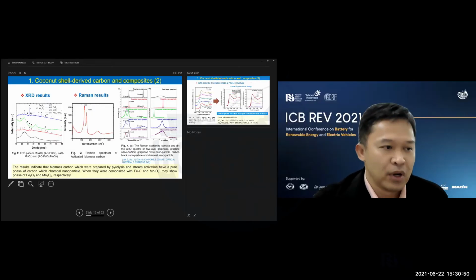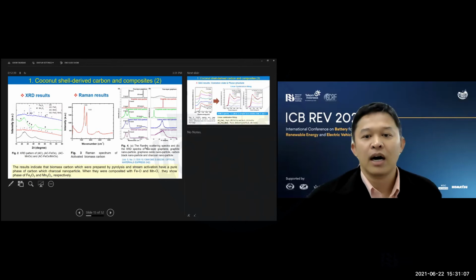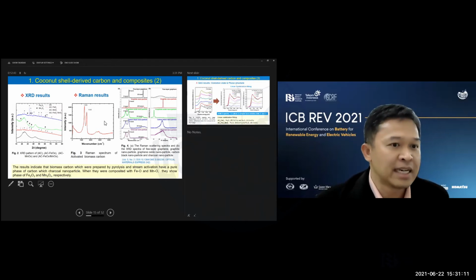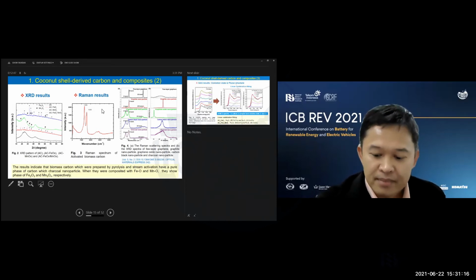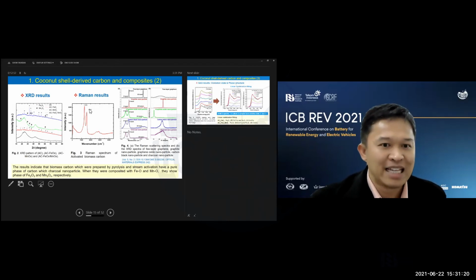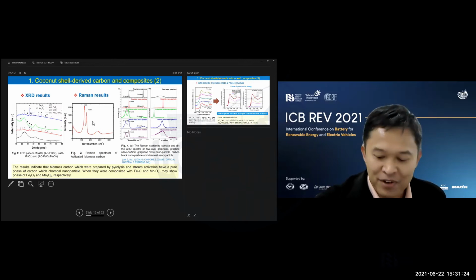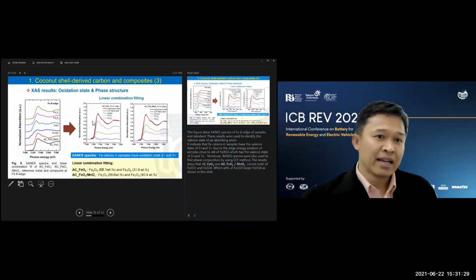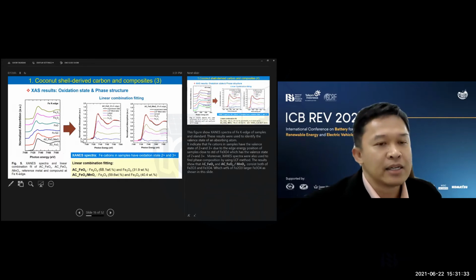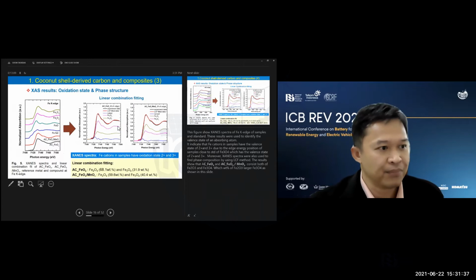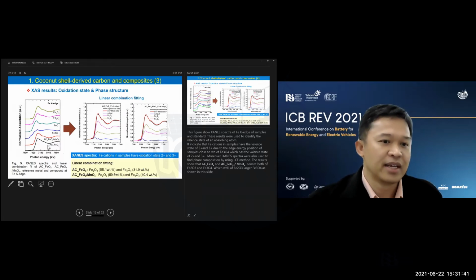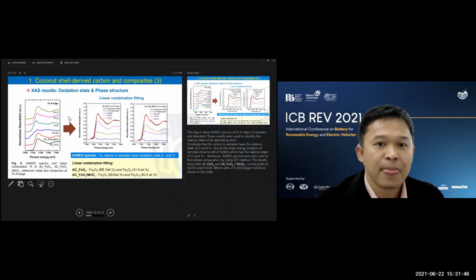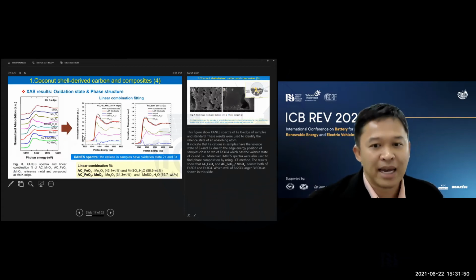After we obtain the products or the samples, we did the characterization using XRD and Raman as the techniques for checking the composition and also the phase structure of the sample. From these two techniques, we can confirm the formation of the carbon-based composite. The Raman results show a very clear D and G peak of carbon, so we can confirm the formation of carbon by using Raman spectroscopy. We also use X-ray absorption spectroscopy to study the oxidation state and also the phase structure of our materials as well. This one is the study of the carbon and also the carbon-iron composite, and the next one is the study of the carbon and manganese oxide composite.